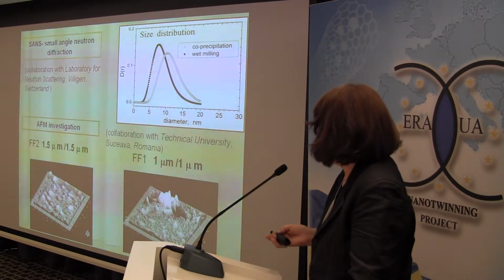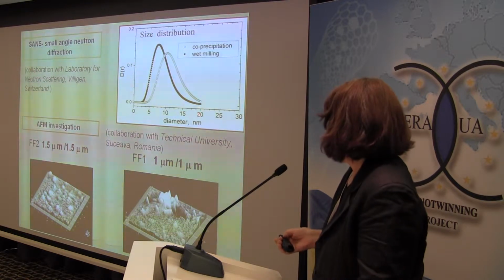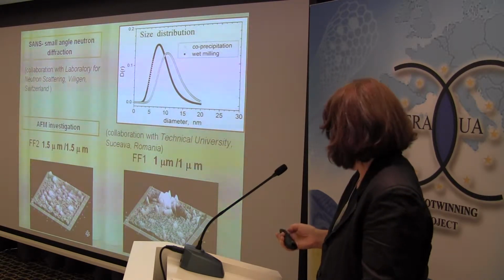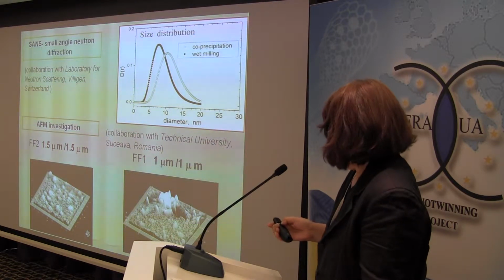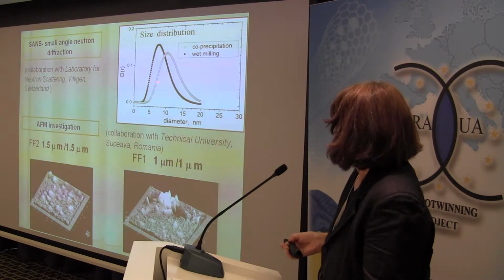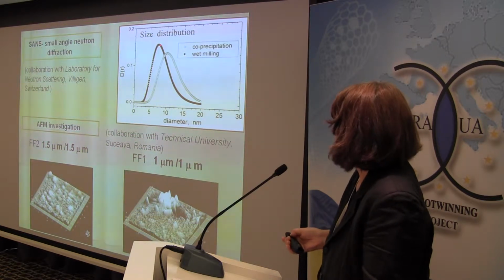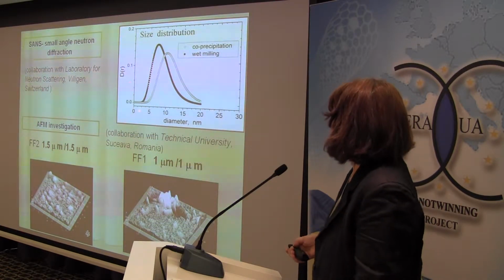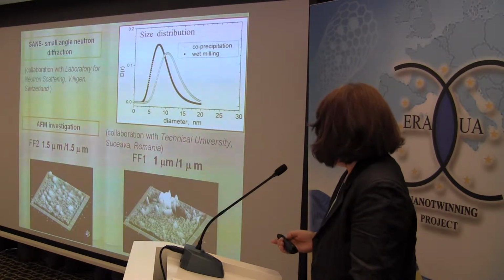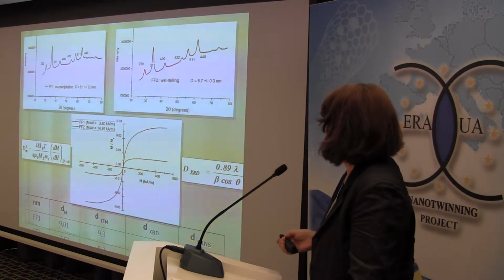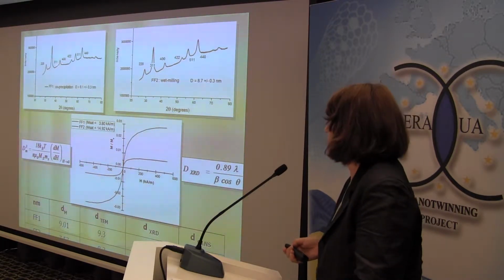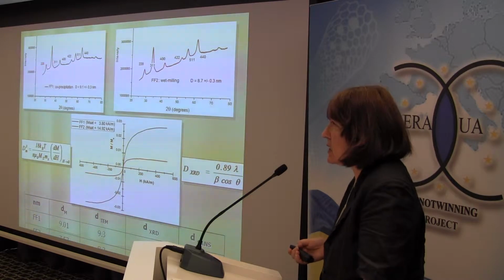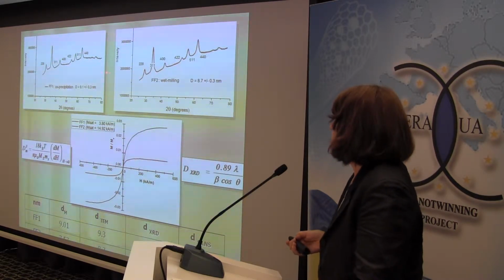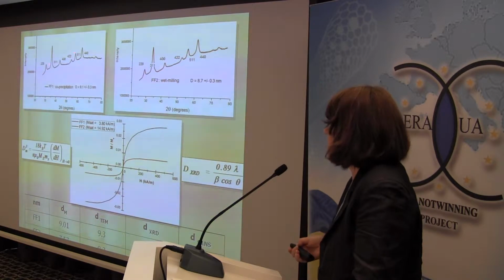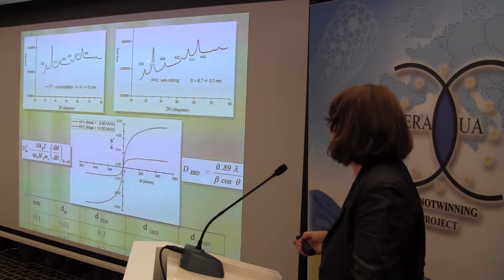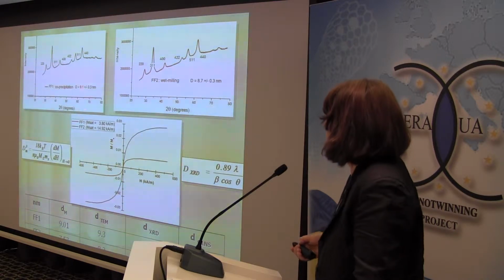So the highest nanoparticles, with rather low frequency, are no higher than 20 nanometers. The main parameter for discussion of stability is the diameter of higher frequency appearance, and this one is small enough in both cases. At the same time, crystallinity was rather good in both situations, with specific peaks of spinel structure. Some artifact resulted from liquid traces within the preparation sample, so the so-called zero line is not so horizontal.